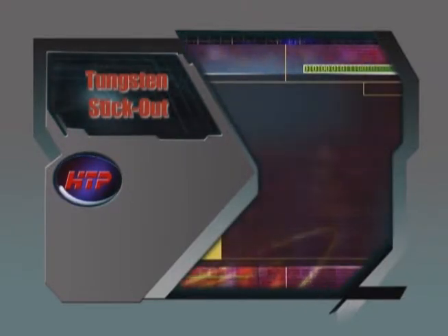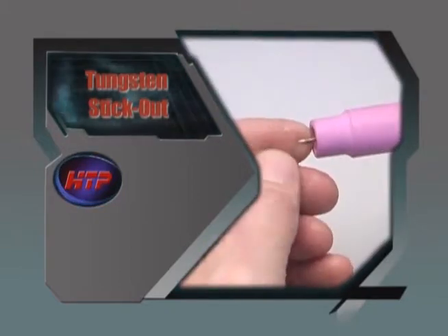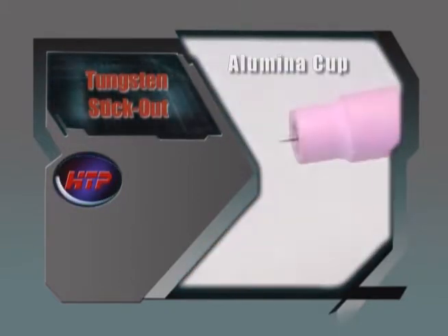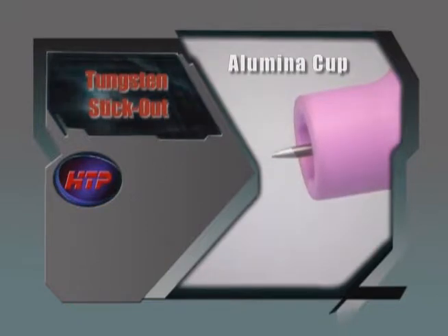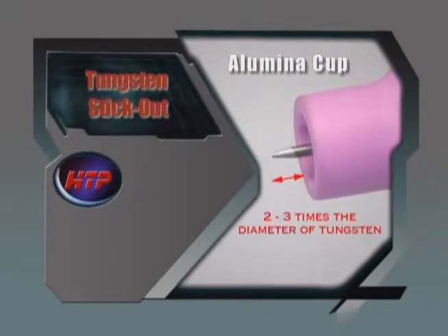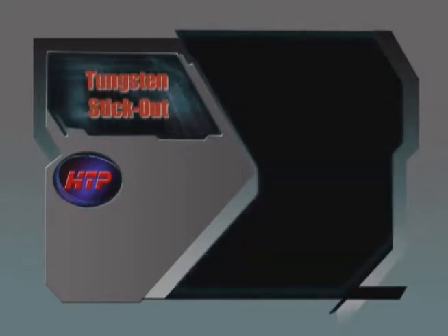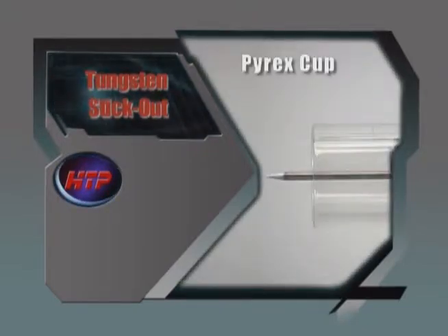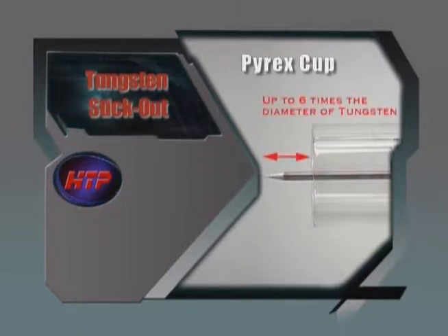The tungsten stick-out is the distance the tungsten sticks out past the end of the alumina cup. This can be anywhere from 2 to 3 times the diameter of the tungsten with a standard cup setup. Using a Pyrex cup or a gas lens and increasing the gas flow will allow you to get a stick-out of up to 6 times the diameter of the tungsten in a draft-free environment.